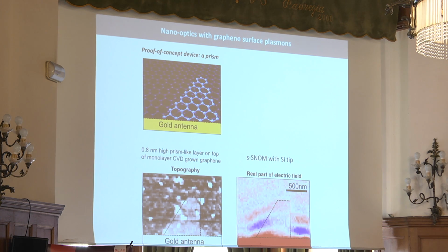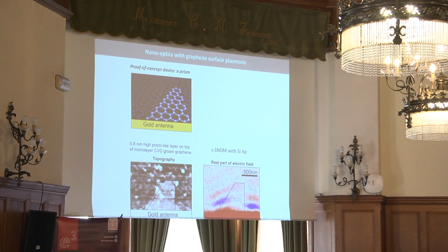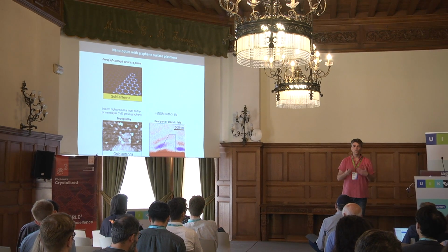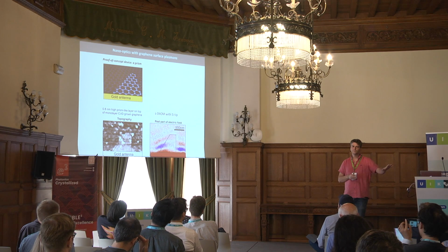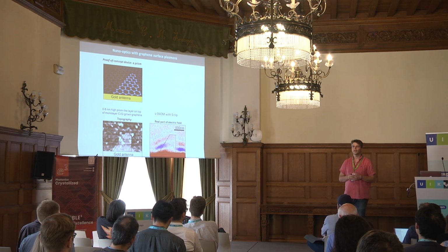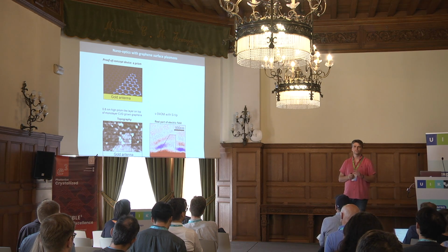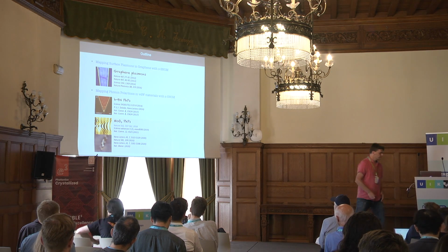And from that time to now, I think the silicon tip has not really been used very often. And I want to draw your attention to this, because sometimes the metal tip, because it's also launching waves, distorts the pattern a lot. And sometimes it's exciting many modes in the field, and they are all interfering. And the mode patterns are really complicated. And if you just use the silicon tip, you are more like looking at the real snapshot of the propagating wave. OK? But with signals one order of magnitude less intense, normally. OK. So with this, I go to the next thing.